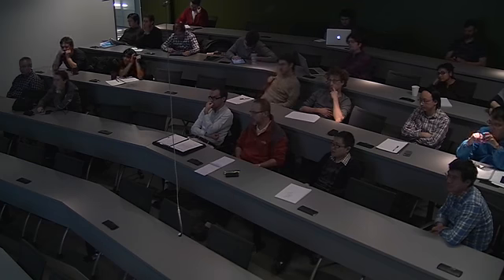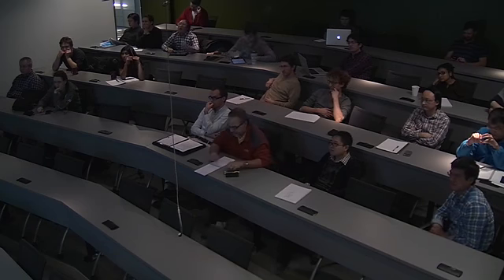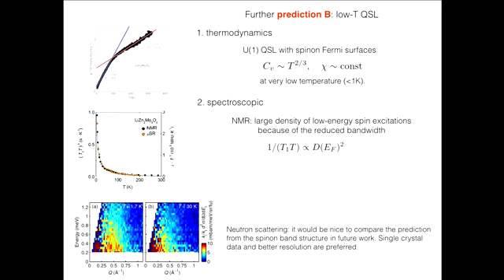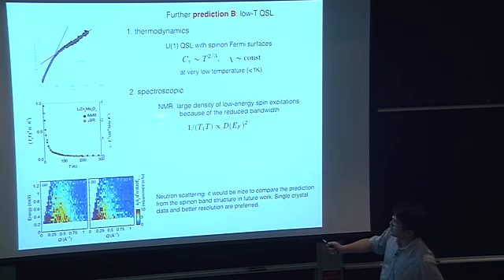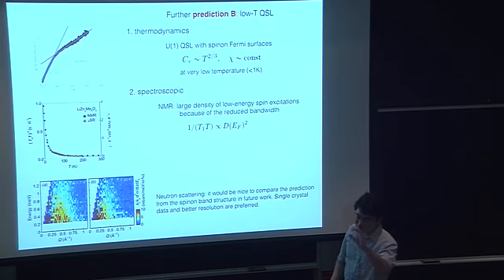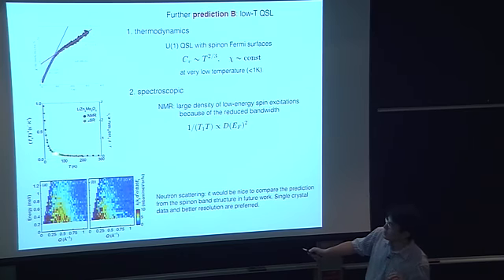So prediction. In the charge sector, we have this first order transition. Okay, so what's the other prediction for the spin sector? The ground state is expected to be a U(1) spin liquid with a spinon Fermi surface. We have a T^(2/3) heat capacity and constant chi at very low temperature because the temperature scale is very small. So in order to see this, you need to go to very low temperature. Spectroscopically, in NMR, measure the 1/T1T, the spin lattice relaxation rate. This is proportional to the density of states. Because of the reduction of the spinon bandwidth, the effective density of states is enhanced at very low temperature. That's why there is a big peak in the 1/T1T measurement.